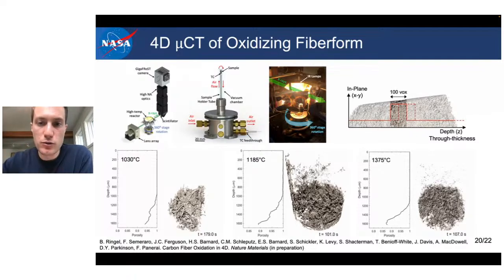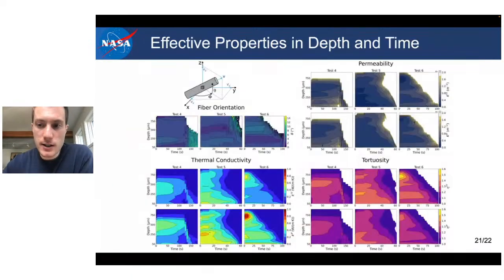And until you do this process throughout the thickness, and then also throughout time. These are the results, which I obtained very, very recently. We ran this study for conductivity, permeability, and tortuosity. What you can see here is that the two rows correspond to the through-thickness components of the material properties, and the in-plane is below.